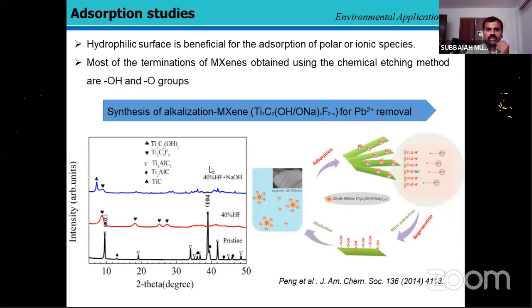They confirmed that the sodium ion was intercalated rather than forming an upper layer. This surface adsorption, it was intercalated between the layers, was confirmed by PXRD studies. You can see here there is a pristine form of MXene. Then the d-space of 002 has been shifted towards the lower angle of 2 theta, which confirms that the structure has delaminated, which means that sodium ion has incorporated between the layers. Sodium ion has incorporated between the layers, so the sheets get exfoliated.